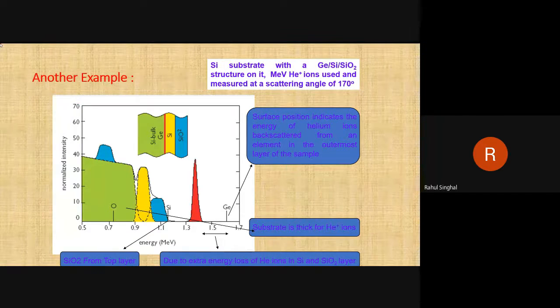In this other data, now we have many elements present. This is our silicon bulk, meaning the silicon substrate, over which first we have a germanium layer, then another silicon layer, then a SiO2 layer. Suppose I want to see the RBS pattern of this. In the RBS pattern you have germanium, silicon, and oxygen. So three elements are mainly present. Among these three, germanium has a higher mass than silicon, and then oxygen. Because germanium has the highest mass, the germanium peak should come at the highest energy, like here, at 1.3 to 1.5. After that the silicon peak comes like here. Then there is one more peak on silicon depending on its width in the sample, and then there is a big peak here.